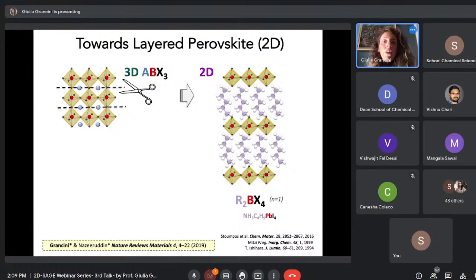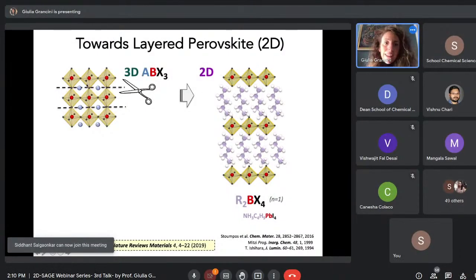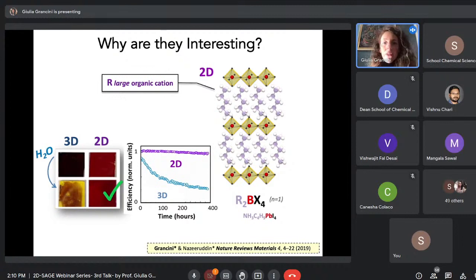So my group is working on a different class of materials which are called 2D perovskites, which you can obtain by simply imagining to cut the 3D perovskites along the inorganic planes. So you have single inorganic layers which are spaced by large organic cations, ending up with this formulation. Why are they interesting? Because with respect to the 3D perovskites, they do not show any visible degradation upon exposure to water and humidity. So the stability reported here, that is basically the efficiency under time, is much enhanced with respect to the 3D.